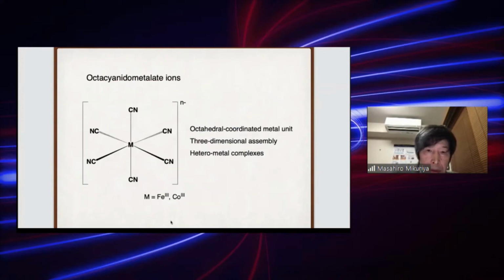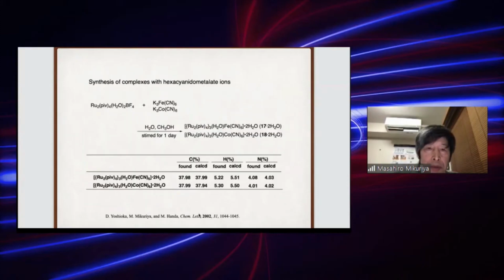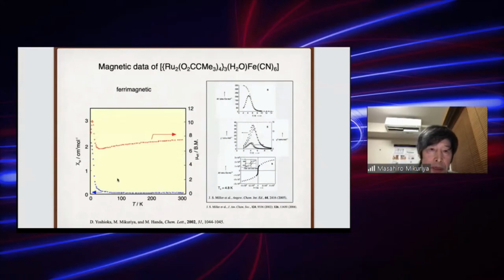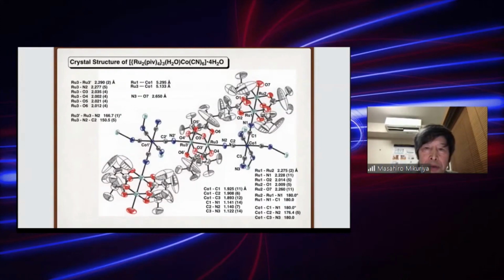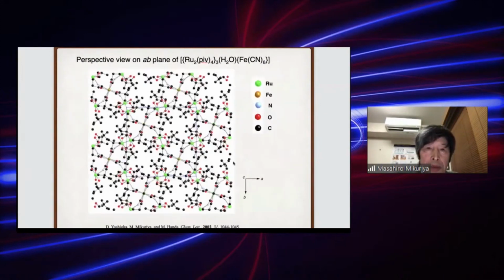So, to make magnetic material with three-dimensional linkers are much better. So, for example, octacyanometallate, using this unit, we obtained ruthenium-II,II and cobalt species many years ago. And this one has ferrimagnetic interaction, and Miller's group also studied in more detail, and what a beautiful result. In our case, we obtained crystal structure for this compound, like this.